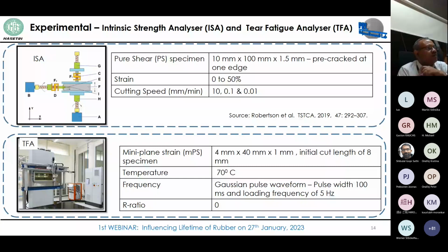In the tear fatigue analyzer, for the stable crack growth zone, a mini pure shear or mini planar strip specimen was used with the following dimensions, and temperature was kept at about 70 degrees centigrade. The loading was a Gaussian pulse waveform with a pulse width of 100 millisecond and a repetitive frequency of 5 hertz, which was again taken from the previous slide. If you recall, the loading pattern is more of a pulse in nature compared to sinusoidal, and R ratio was kept 0.